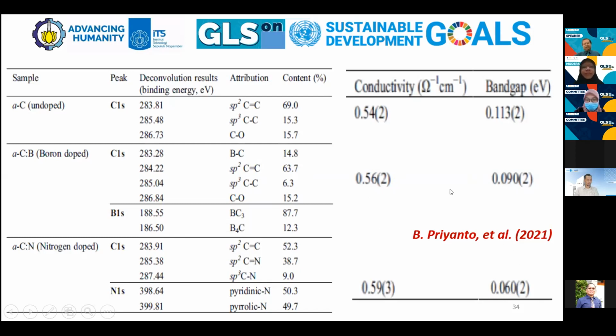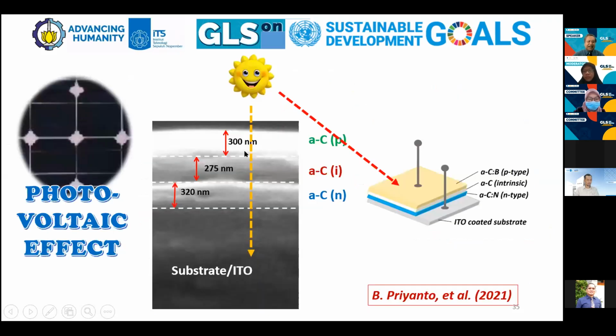As we compare with the conductivity of amorphous silicon, this value is more than 10,000 times higher for the amorphous carbon. Next, we have fabricated a PIN junction where it's layered with the thickness of about 300 nanometer. You can see here.